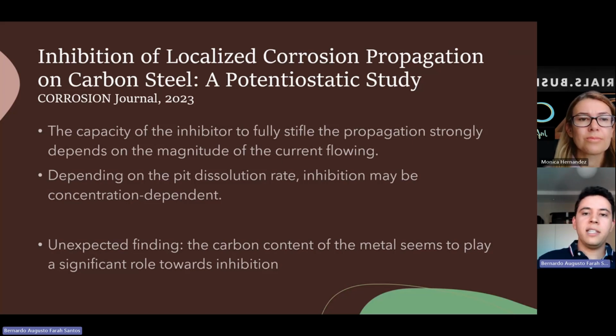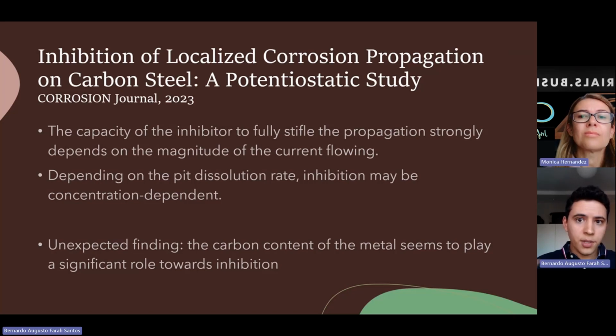And one unexpected finding that we found out is that the carbon content on the metal substrate that you're testing is detrimental for the effective inhibition, because we figured that whenever you corrode your sample severely, you end up revealing the iron carbide on the surface, and the iron carbide might lead to poor inhibition. So that was something that we were not counting on, not even expecting. Of course, that's research, but that was surprising, and that makes a lot of sense, mainly considering everything that was written and published in the literature.